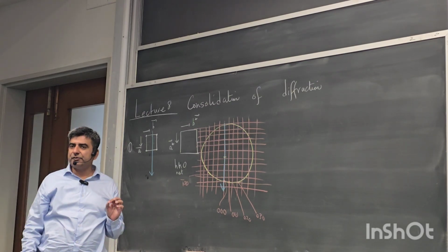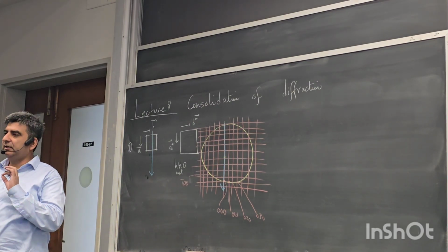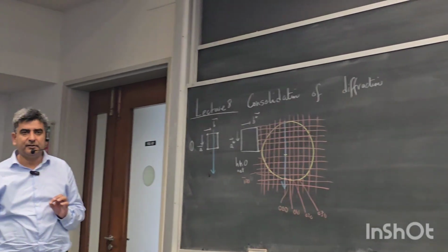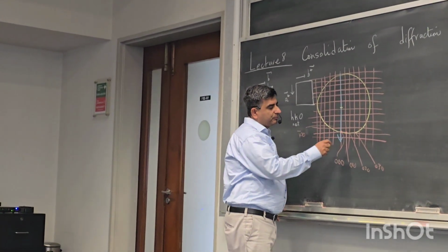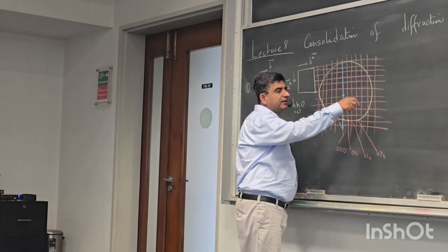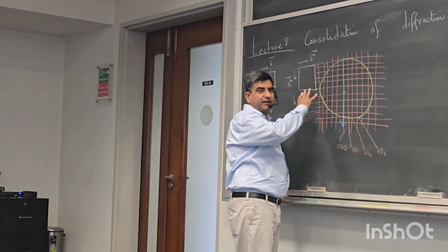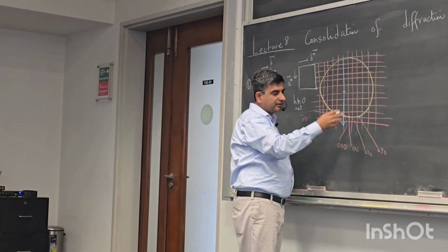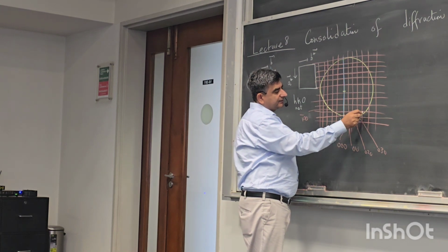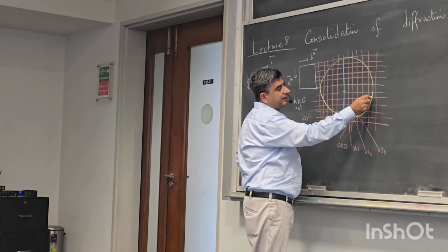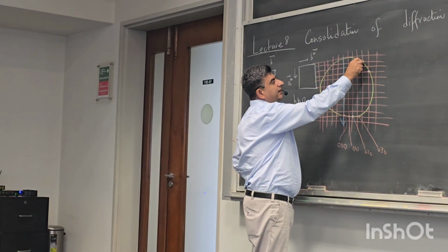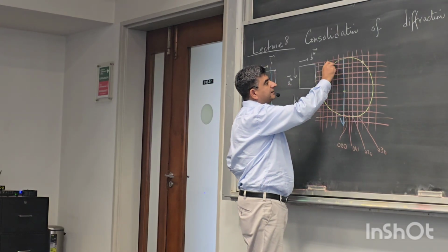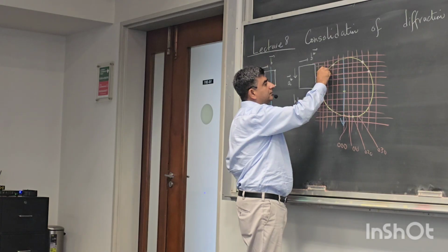Okay, and then in order to see the allowed reflection directions where scattering is taking place, we look at whether this Ewald circle, it's really a sphere, but in this net it looks like a circle, cuts at points where there is an intersection between the circle and the reciprocal lattice points.